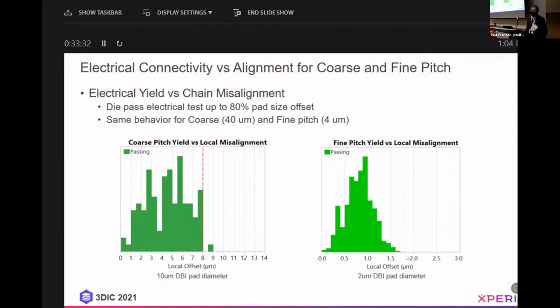So that's a good question. At 50 microns, the wafers are already getting pretty fragile, the die. And so a lot of that depends on the pick and place tool, having it set up so that you don't crack the die when you peel them off the tape and that sort of thing. I know die are being stacked currently, I think for HBM, with thinner than that. So it is possible to handle the parts, but a big part of it too is managing the processing of the wafer so you don't create weakness in the silicon during the processing. If temperatures are too high or that sort of thing, we've seen creation of weakness in the silicon itself, which can cause cracking, potentially from the expansion of the TSVs during the processing.